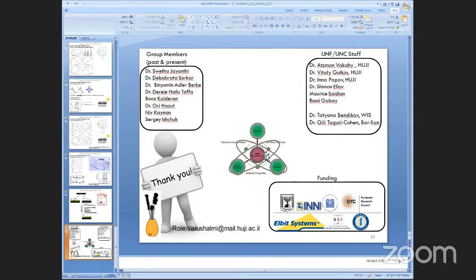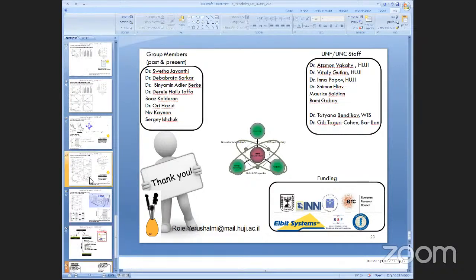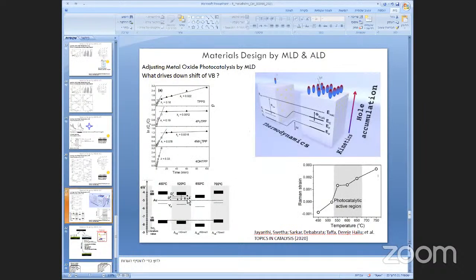Yes, so defects are very important for the performance of these materials. For example, if you look here, these intermediate electronic states form because of defects, and they allow the fast electron transfer of photoexcited electrons to the gold nanoparticles, and therefore we can overcome the well-known kinetic barrier of oxygen reduction, that is typically hampering the whole hydrogen peroxide production. So of course, this is a very important feature.